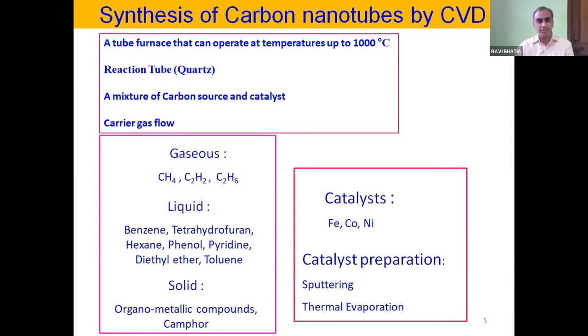And catalyst preparation, sometimes the carbon nanotubes are grown in a two-process method. In the first, the catalyst is prepared using sputtering or thermal evaporation, and then that substrate is placed inside the reaction tube having a facility of reaching 1000 degrees C and you just provide a carbon source there, and carbon nanotubes can be grown. So the first complexity in this system is to have a two-step process of the carbon nanotube production. One can remove this by using a single source, for example, ferrocene or nickelocene or cobaltocene, because it itself provides both carbon source and catalyst. But in this case, the quality of carbon nanotube is compromised.